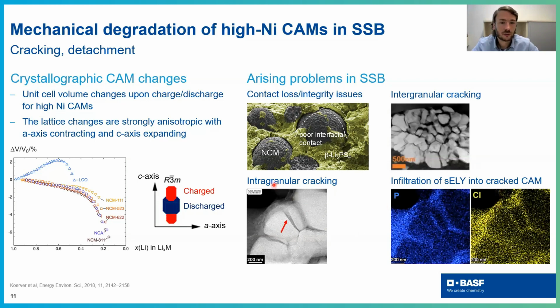Now, why does it happen? Well, you know that the high nickel material, but actually also NCM material and LCO, they all experience certain volume changes during the charge and discharge. And these volume changes are of anisotropic nature. During the charge, you have two crystallographic axes, a and c, and a is contracting, c is expanding, then c is contracting again. So you have a lot of different changes, and in this polycrystalline particle, like shown here, for sure, you have a lot of strain, which leads to this cracking between the particles. And because of this strain, probably you also have intragranular cracking, so that even single crystallites can break. Now, how to deal with that?